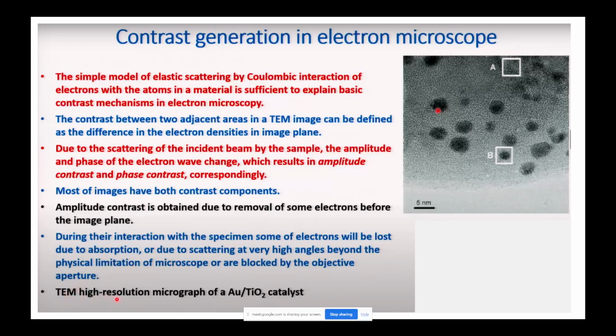So, the TEM high resolution micrograph of a gold and titanium oxide catalyst, here you can see. This is very high resolution. Just see the scale. This is 5 nanometers. How small. So this dot would be around 2 nanometers, around 1 to 2 nanometers. Very, very small. So, nanoparticles.